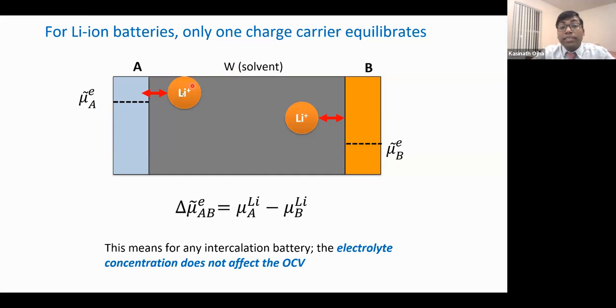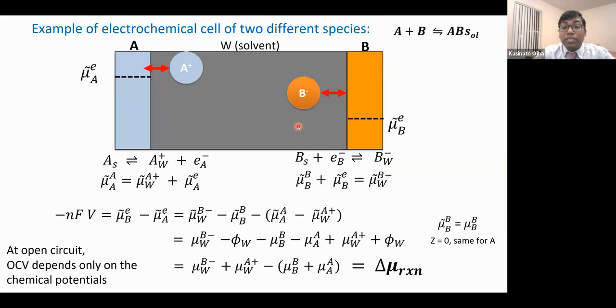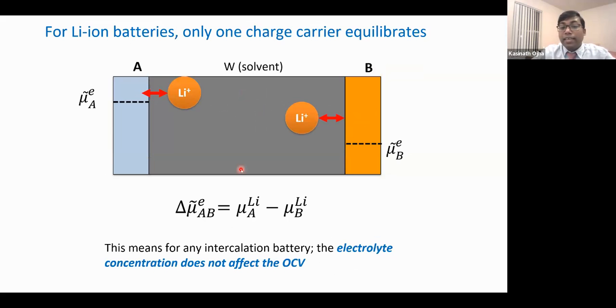And as both are the same ions, if you do the same exercise, we get an electrochemical potential difference, that's basically the chemical potential difference of lithium in the two different electrodes. So in any intercalation battery, particularly lithium-ion batteries, the electrolyte concentration doesn't change the OCV, the open circuit voltage.